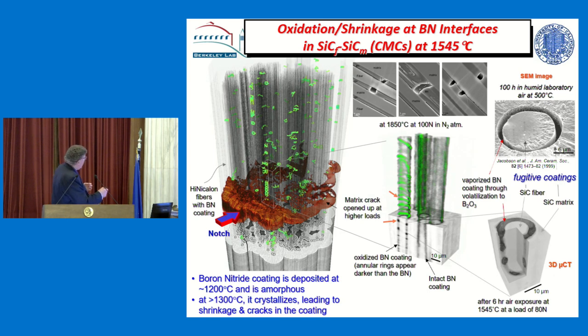It can cause cracks, these little green lines here, in the coating of the fiber. And once the cracks form and these fibers sort of loosen from their coating, there's no more resistance. And so you've lost the toughness because they just sort of pull out. So we can see all this oxidation that takes place and where it's occurring. And you can see exactly where these cracks form. They form in the boron nitride coatings.